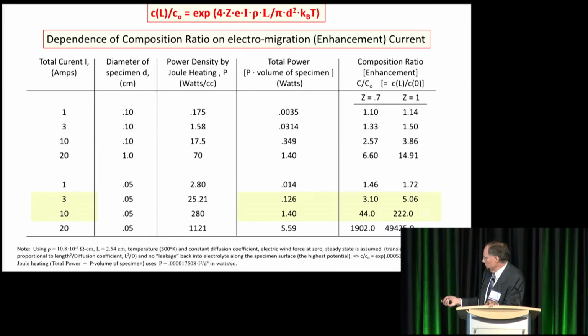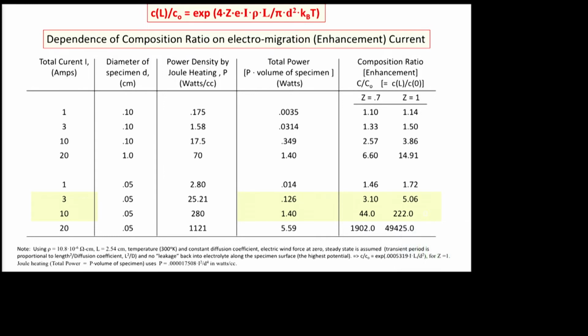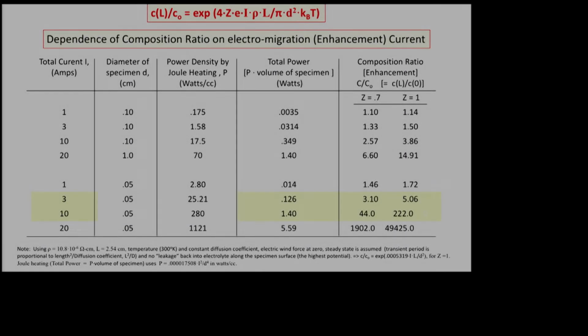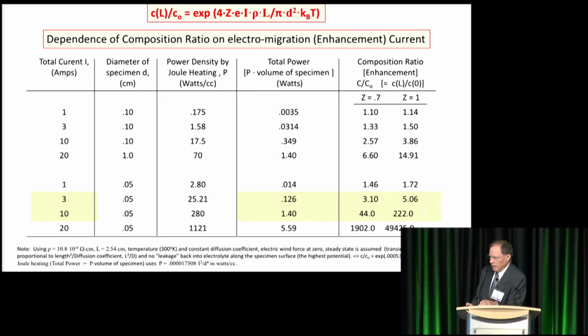And typically in my experiments, I ran around 3 amps continuous electromigration current, which only added about 1/10 of a watt to the system. But on some occasions, I went as high as 10 amps for electromigration, and that still only added 1.5 watts to the cell. However, my sample is very small, so I wanted to keep this down to as low as possible.